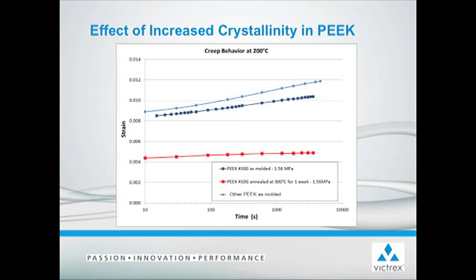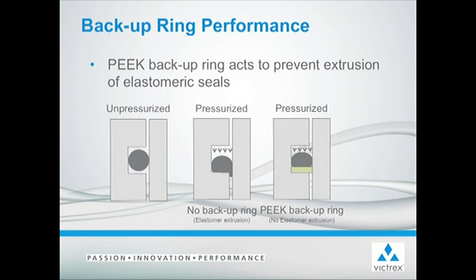More importantly, you can see that the additional crystallinity present in PEEK 450G gives it less creep than other PEEKs at 200 C. However, with high temperature annealing, 450G's creep resistance is vastly improved and between 1/2 and 1/3 that of unannealed PEEK. The illustrations on this slide show how crystallinity and creep relate to backup seals. PEEK backup rings support high differential pressures and elevated temperatures to prevent the failure of elastomeric seals by extrusion.